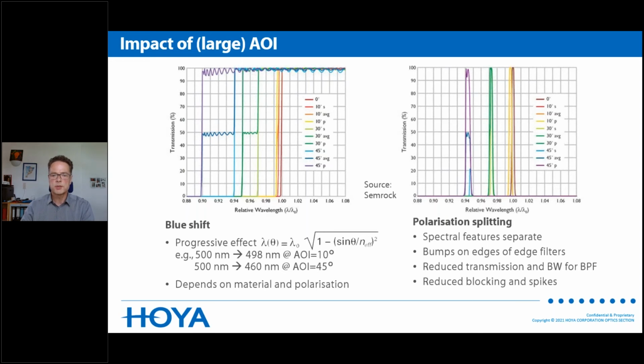This polarization splitting has some severe effects, especially for bandpass filters. And again, you can see for 0 and 10 degrees, it's not really that bad. But for 30 and 45 degrees, the transmission drops rapidly, even more for 45 degrees, and the bandwidth changes as well. What is not shown in these plots is that also the blocking can be impacted. You see a reduced blocking and sometimes spikes in the blocking area. So angle of incidence is something to seriously consider for thin film filters.